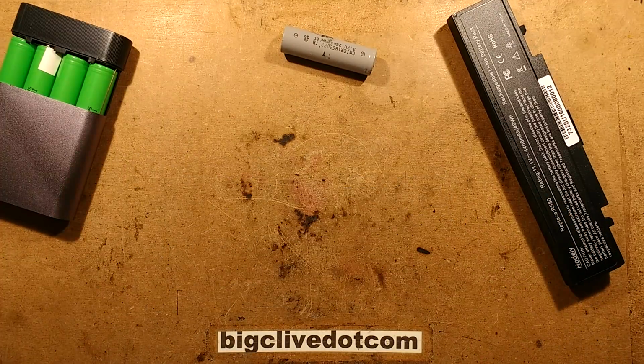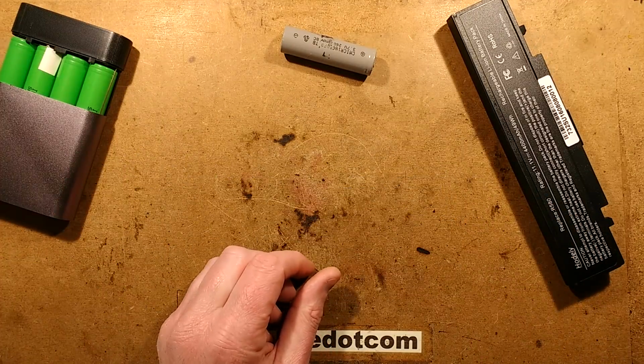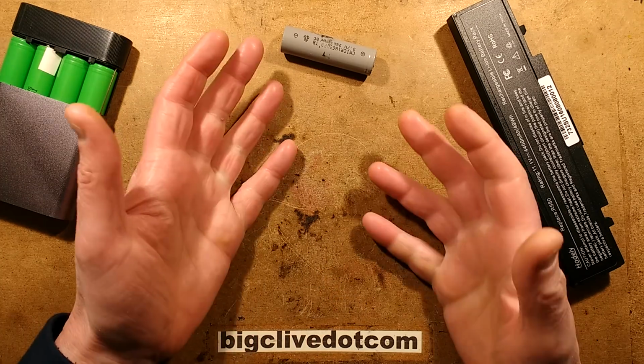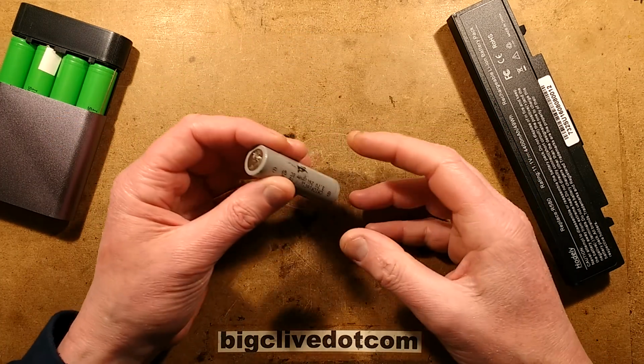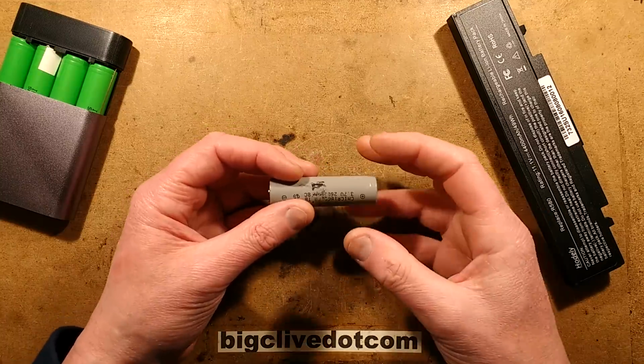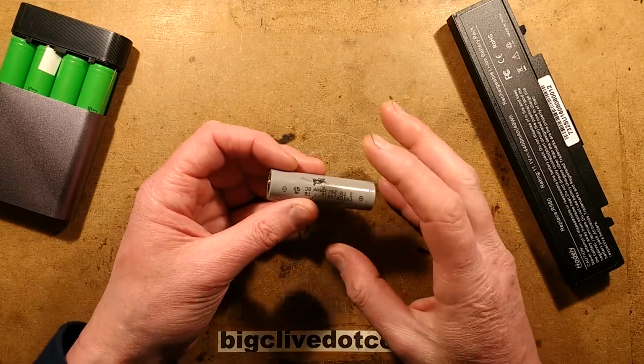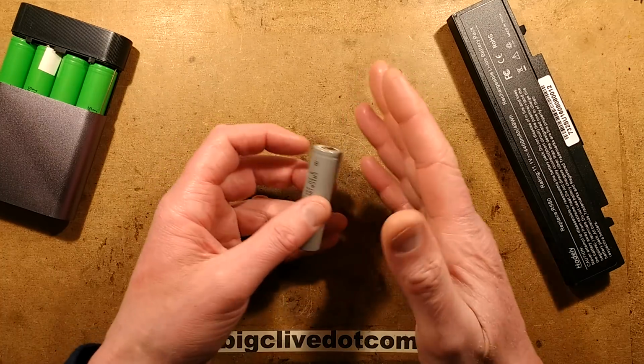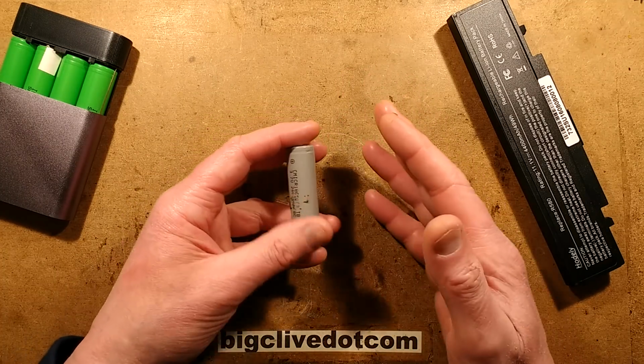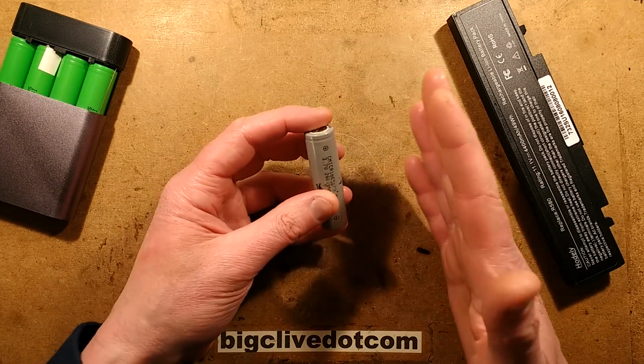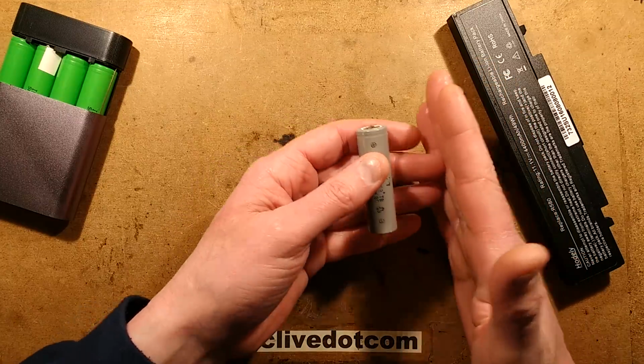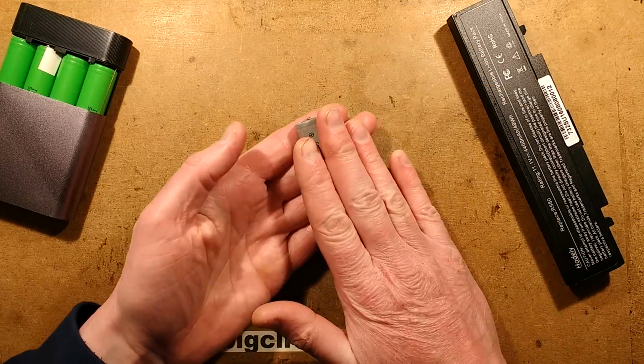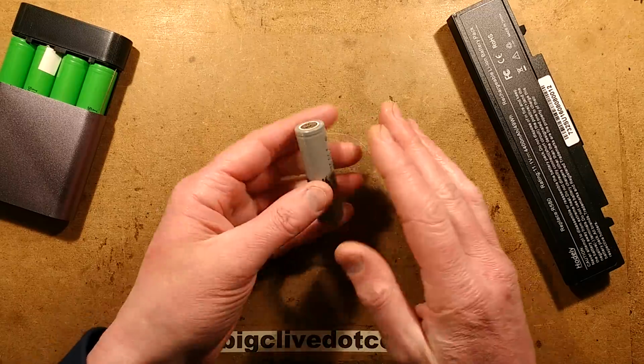And I took apart one of the cells that had failed, two cells had failed, to see if I could see anything obvious in the film, and to be honest, it wasn't conclusive. The only notable thing was that the graphite-type material that stores the electrons, basically hosts the electrons when the battery's charged or discharged, had separated from the copper layer and it had plated onto the plastic separator.